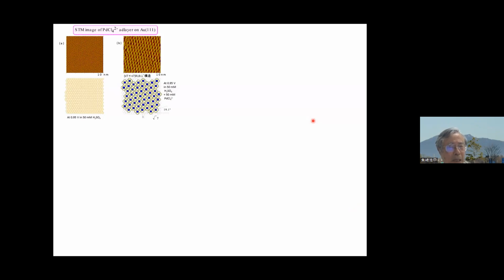So this is the palladium deposition on gold 111 single crystal. This is the STM, scanning tunneling microscope, image in solution. The left-hand figure shows the surface without potassium tetrachloropalladate in solution, so the individual gold atoms can be seen. Then by adding this solution, the surface image changes drastically, and it agreed with this structure corresponding to the adsorption